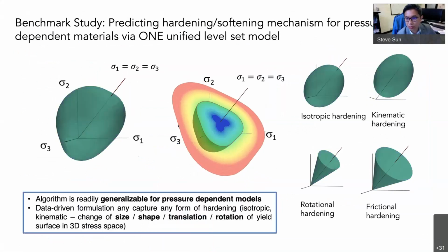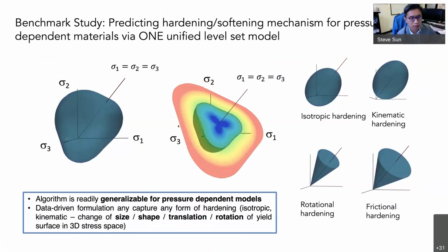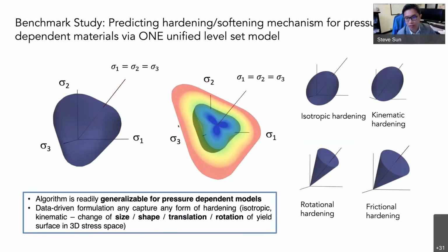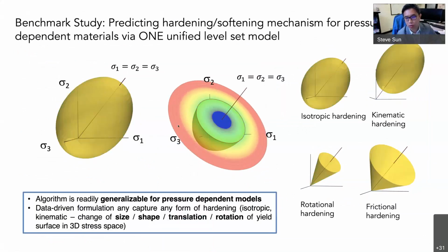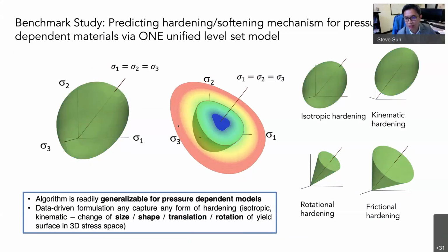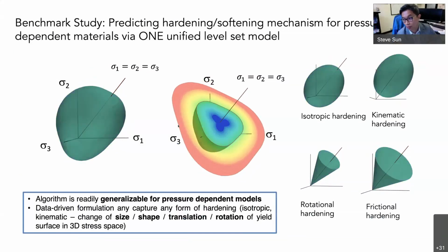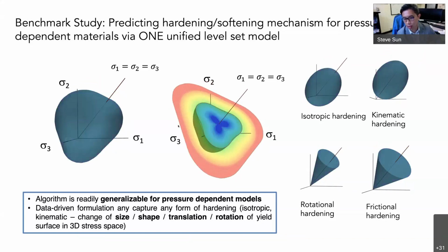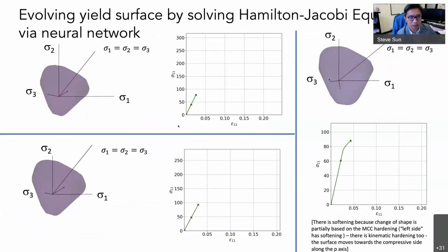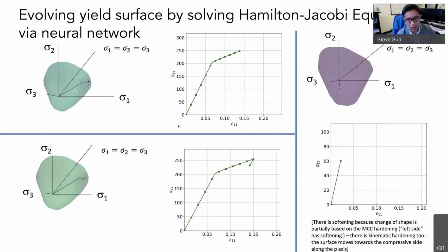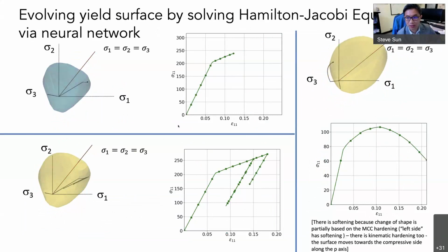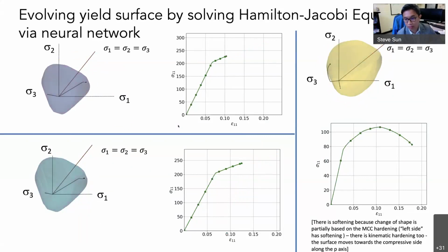And it can reproduce a lot of different plasticity models with various types of hardening. This is exciting because instead of handcrafting different types of constitutive models each time, we can merge all the effort into one meta model. And given different data, it can manifest different types of hardening, different types of yield surface, that in the history of time I handcrafted one by one, in a very time-consuming manner. So this is some response that we see. We identified something very close to Cam-clay plasticity, but it can have a very complicated hardening or softening mechanism in different loading paths.